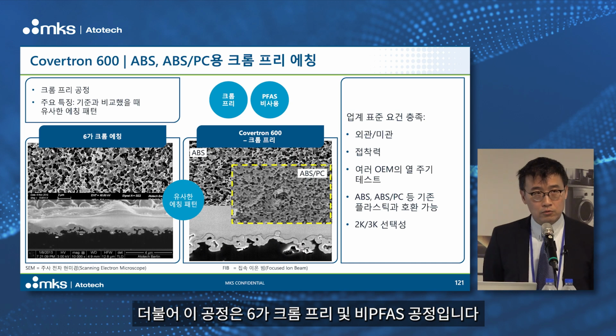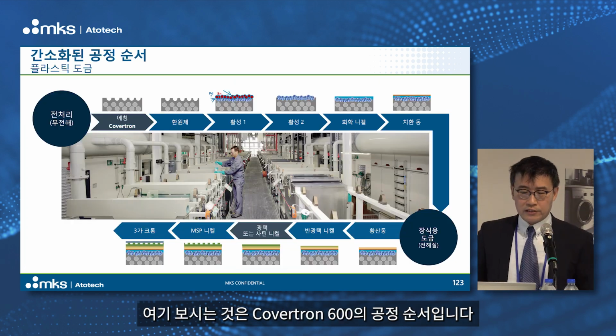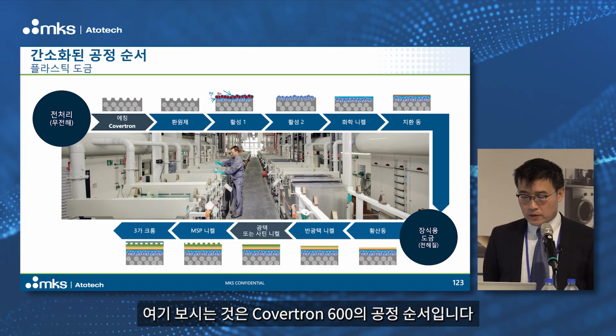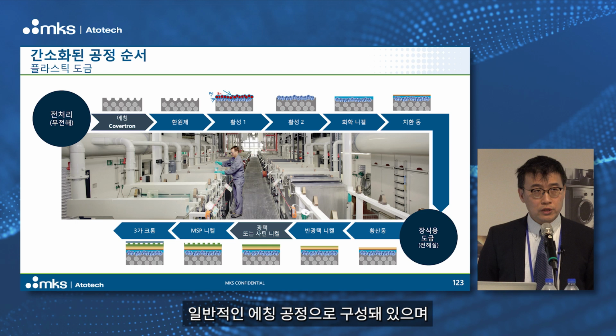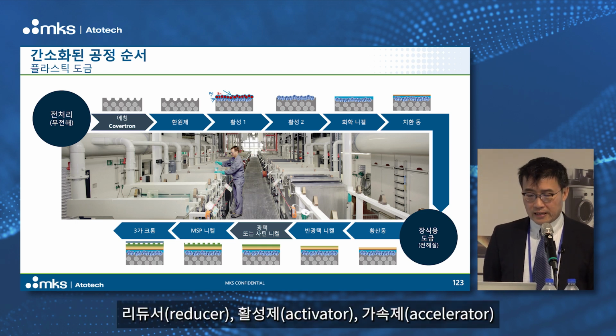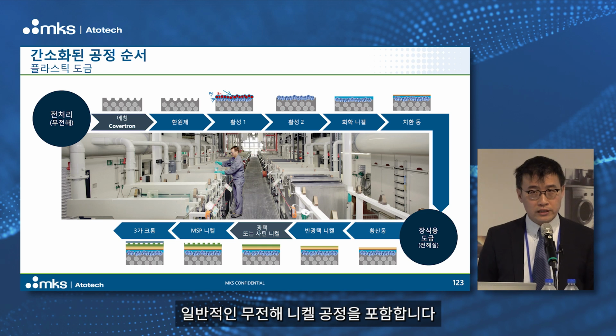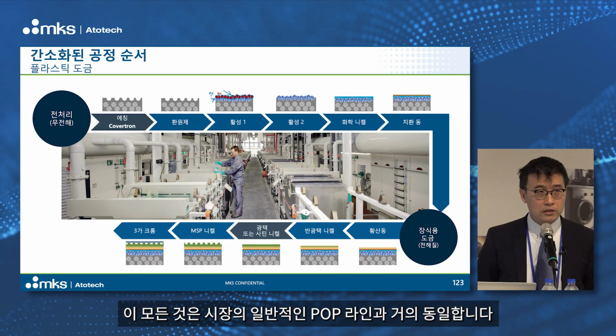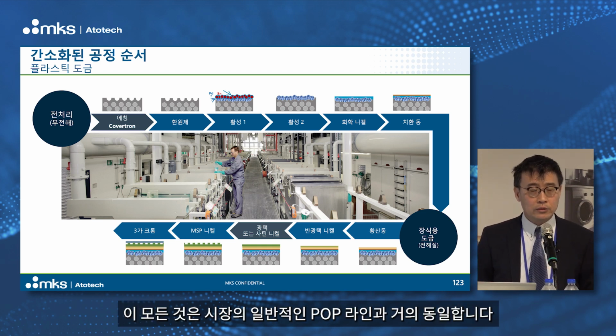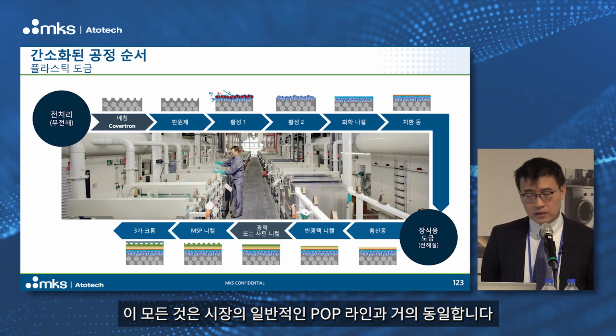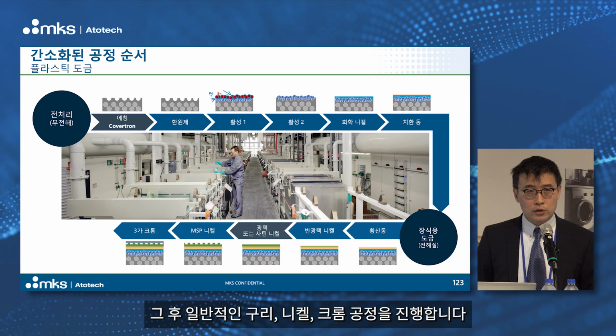And it is a Chrome 6 free and non-PFAS process. You can see the process sequence of Covertron 600. It consists of a normal etching process like the Chromium 6, and then reducer, activator, accelerator, normal electroless nickel process. All of these are almost identical to a normal POP line in the market. And then after that, we go through the normal process like copper, nickel, chrome.